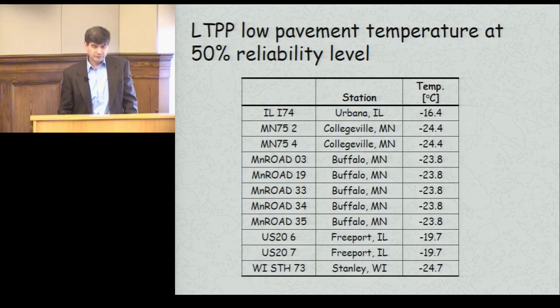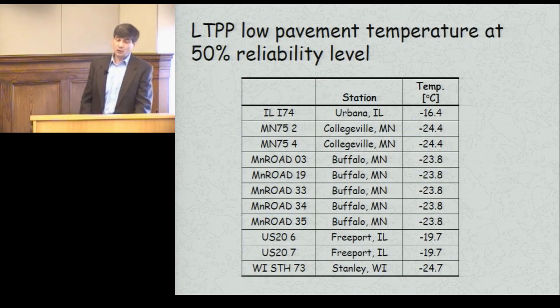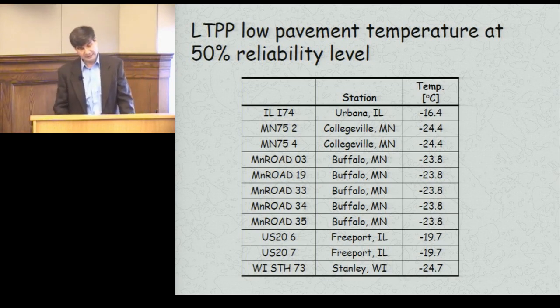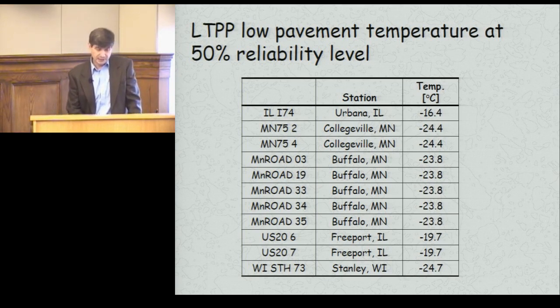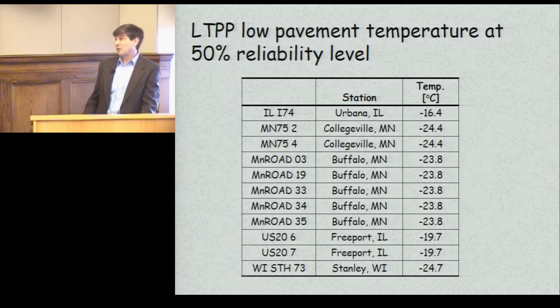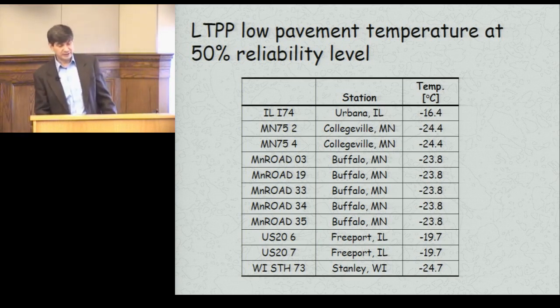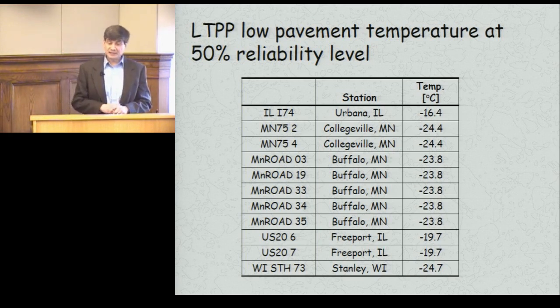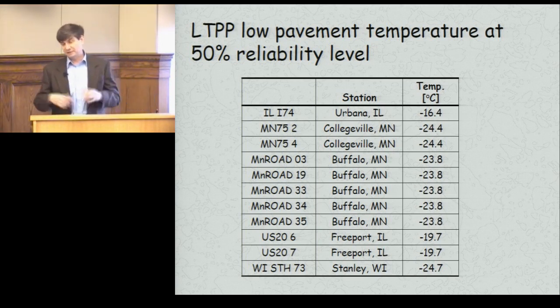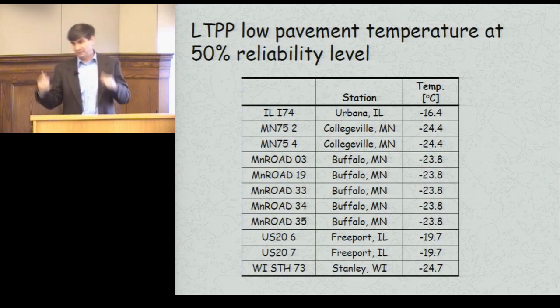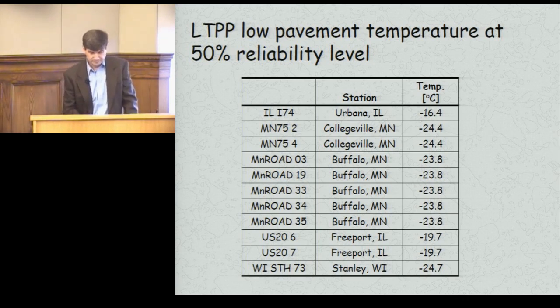And we performed tests at temperatures that would match the low pavement temperature at 50% reliability level according to LTPP. If you look at some of the numbers here, for Minnesota, this is MnROAD facility, that temperature is approximately -24 degrees Celsius, which basically represents a PG asphalt binder of -34 plus 10 degrees Celsius, as I mentioned to you before. So there is some science behind it, so to speak.